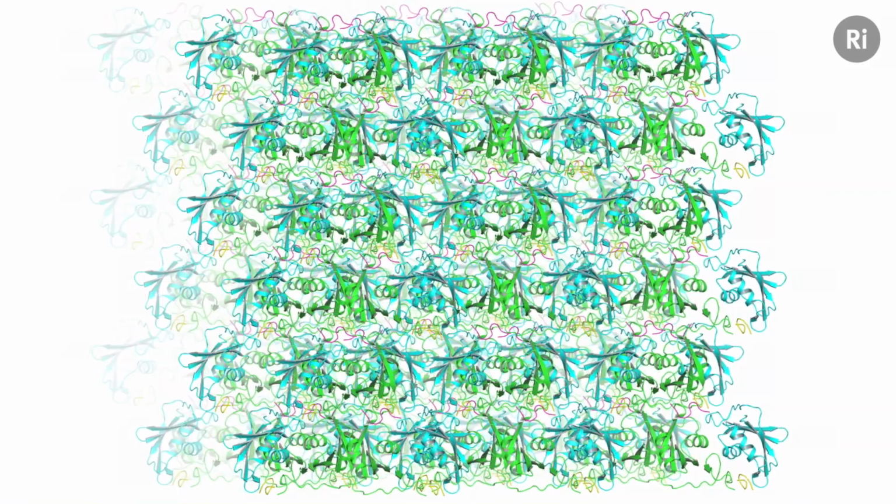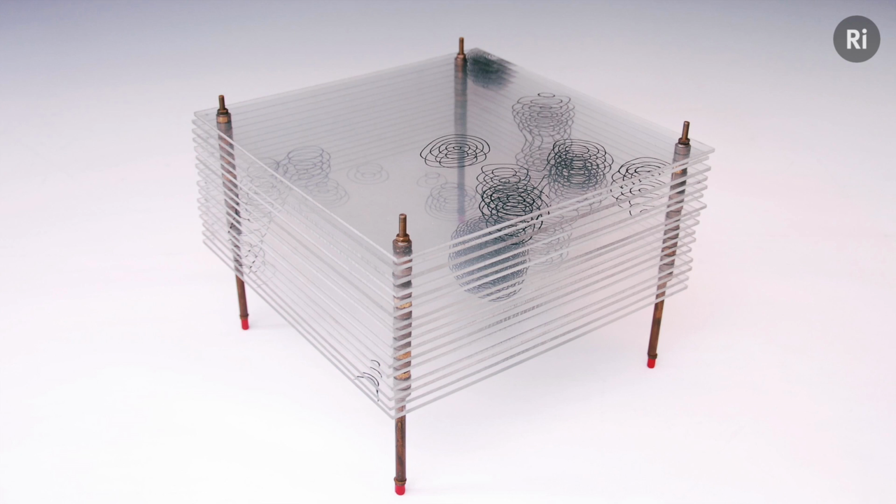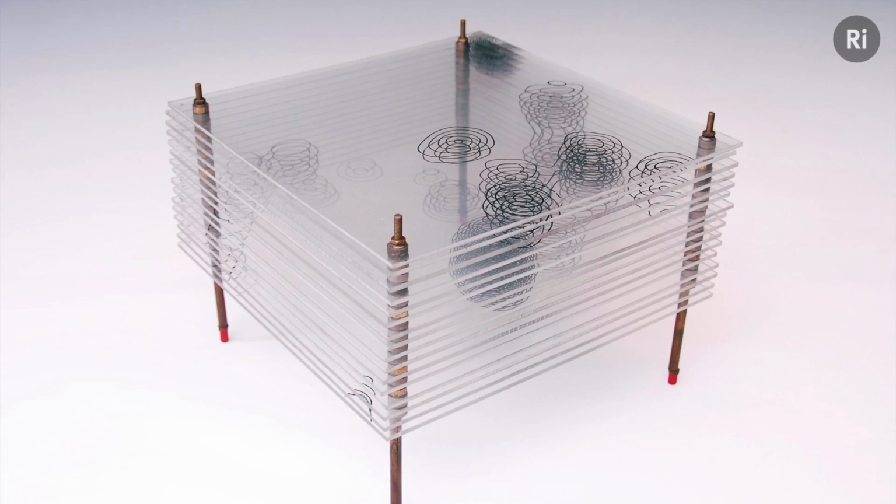What we derive from the experiment are intensities. So if you imagine a wave, the height of that wave, as I'm drawing it, would be what we call our intensity. We can then work out, by the same mathematics that they used 100 years ago, a Fourier series. And it's the Fourier series which enables us to reconstruct the electron density that's inside that crystal. And the peaks in the electron density are the atoms, and that is because we're diffracting the X-rays from the extranuclear electrons. Instead of having to calculate each Fourier layer slowly by hand, plotting it out carefully with contours, the structures now will evolve before your eyes, if you like, on a computer screen.